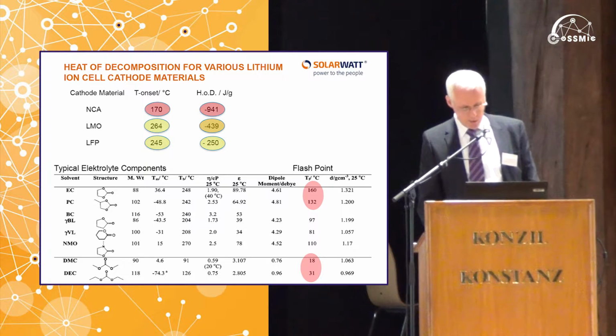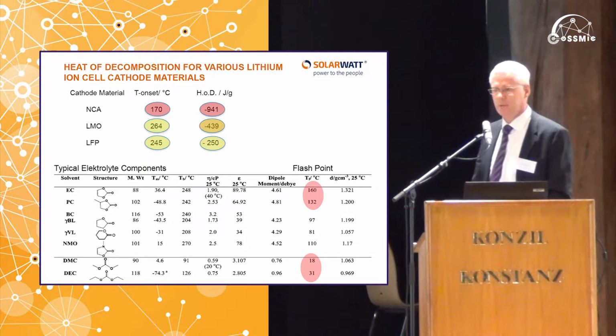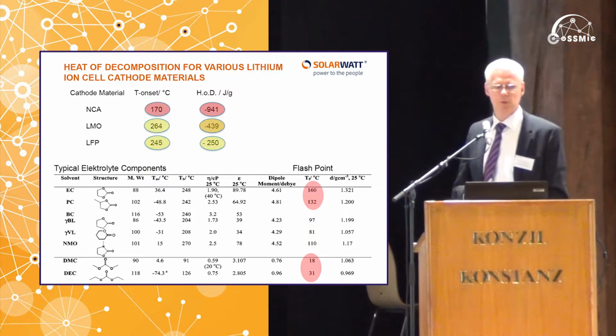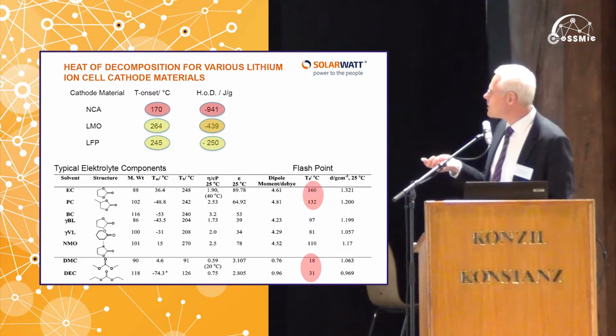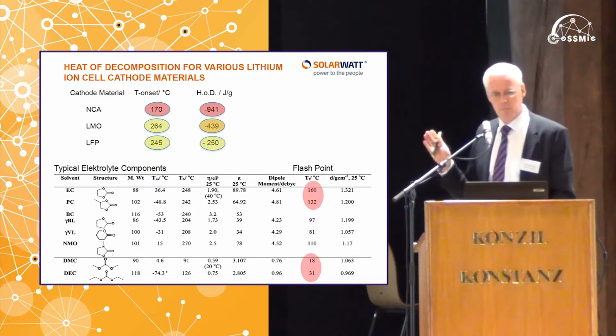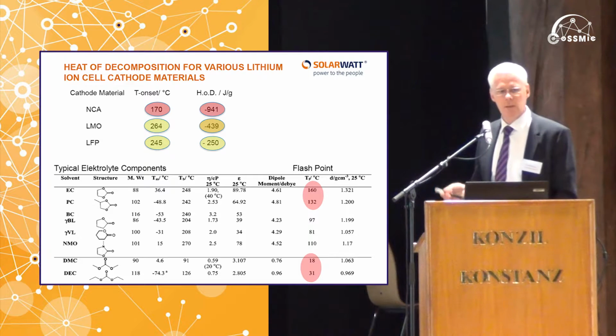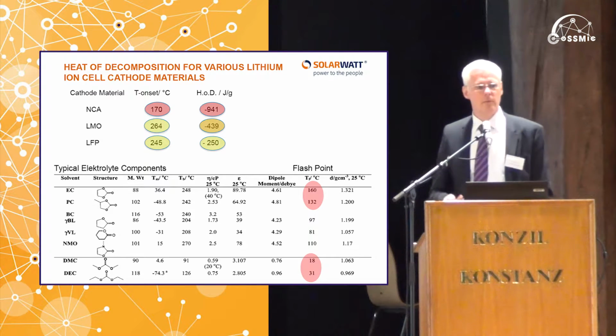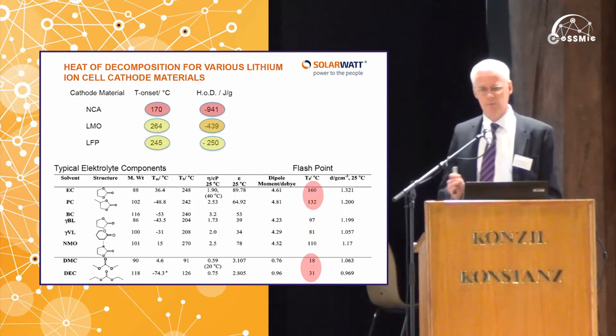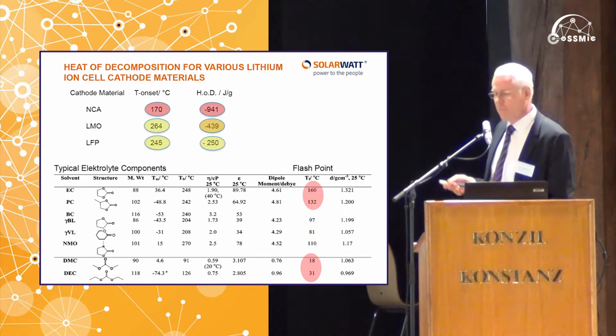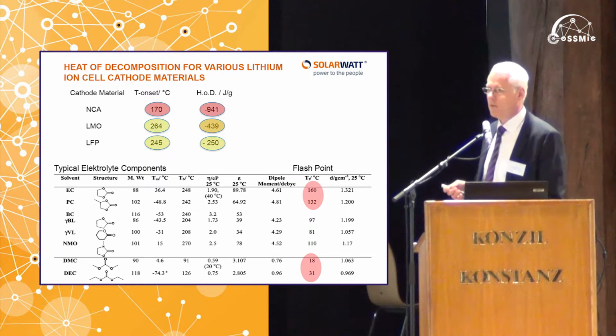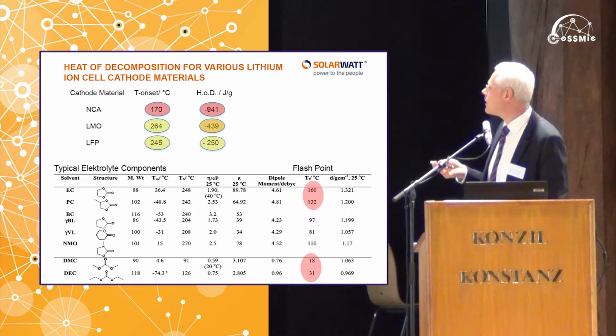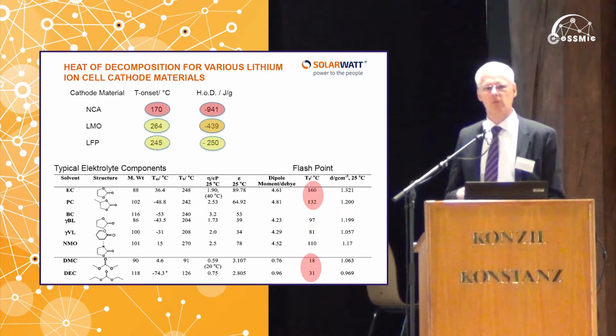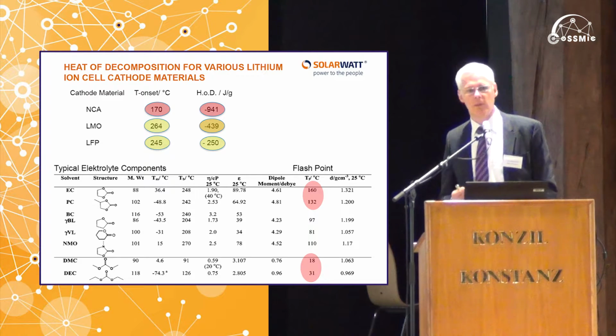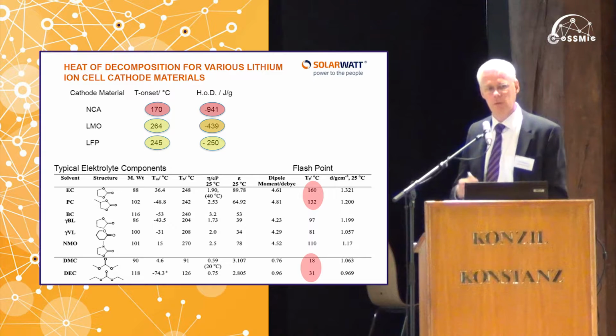Now for the technology inside, there are many options. We have a large variety of cathode materials for the lithium-ion cells. Not only these three that are mentioned here, there are a number of further materials, and they all differ in specific energy, that is the energy divided by the mass of the system, or in energy density, which is the energy divided by the volume of the system. And they differ also in some electrochemical and thermochemical parameters, like here the onset temperature. This is the temperature at which a thermal runaway of the system starts. That means it's a chemical reaction, self-propelled, you cannot stop it anymore.